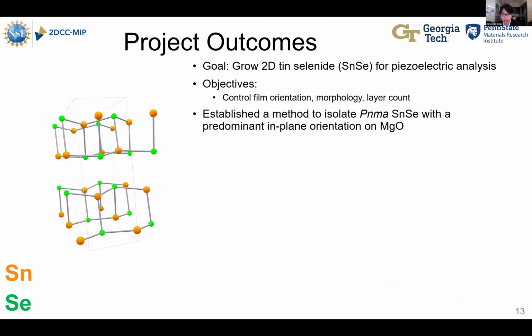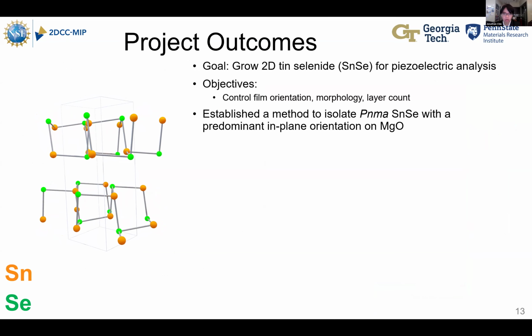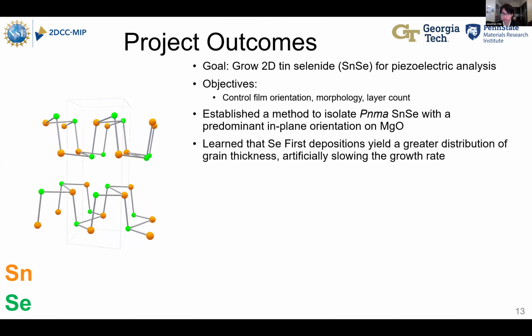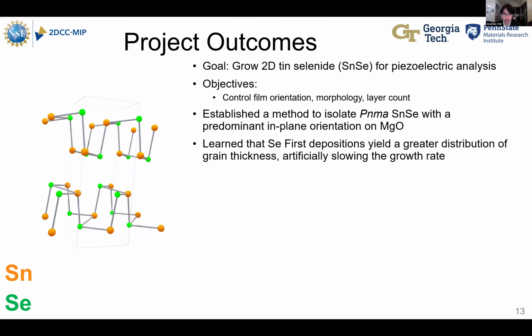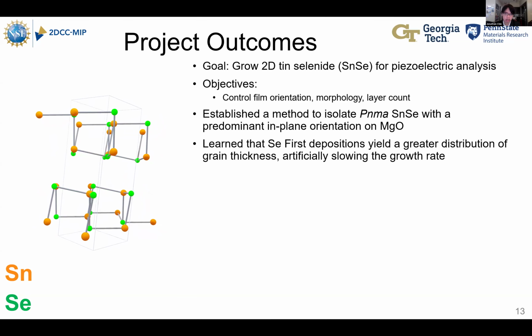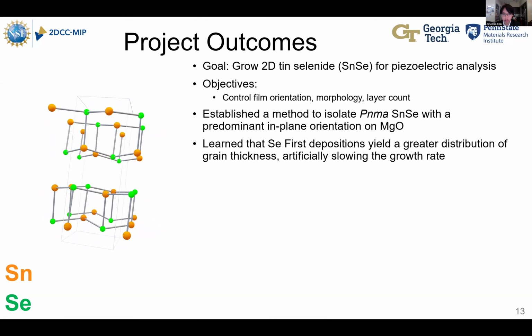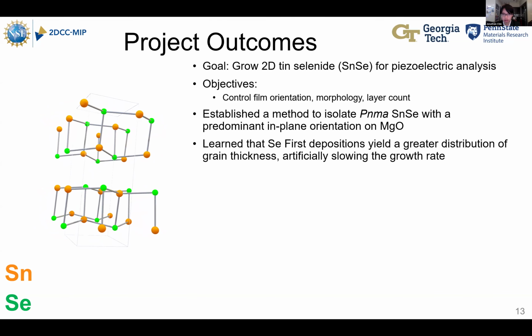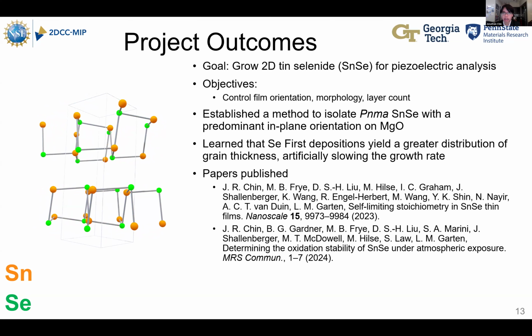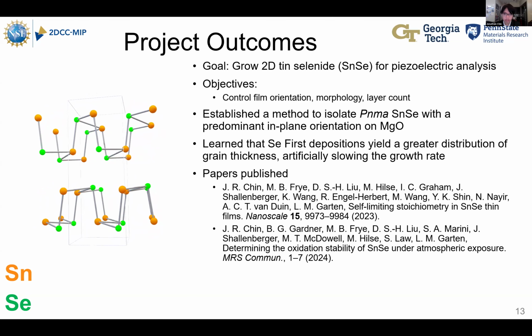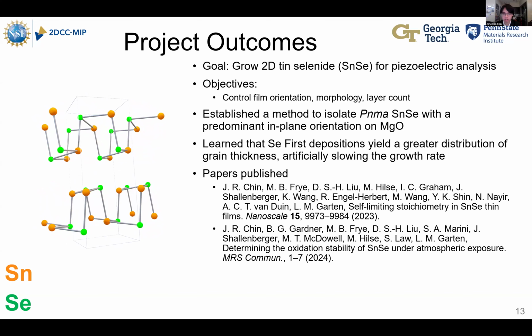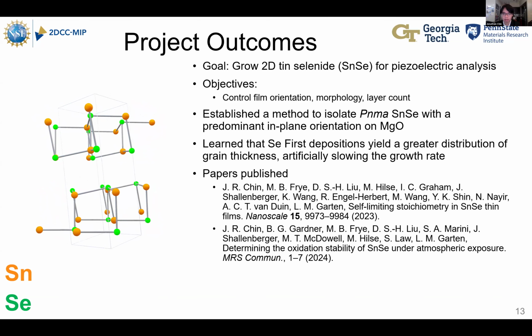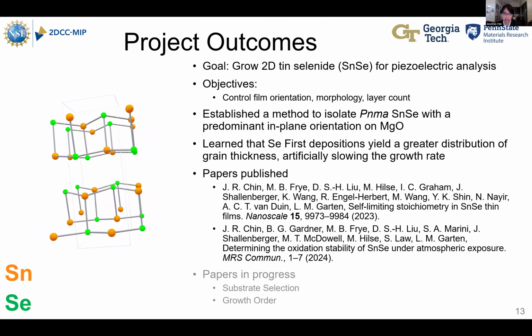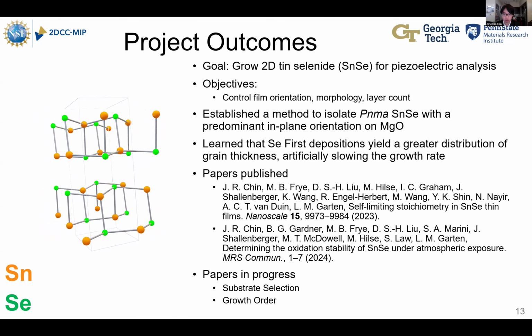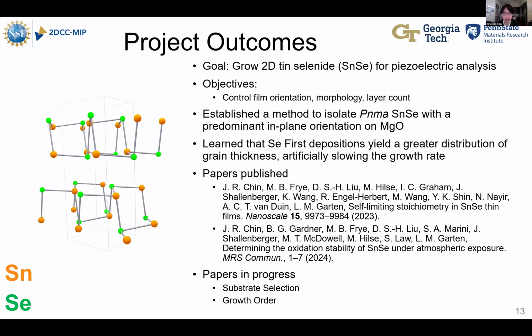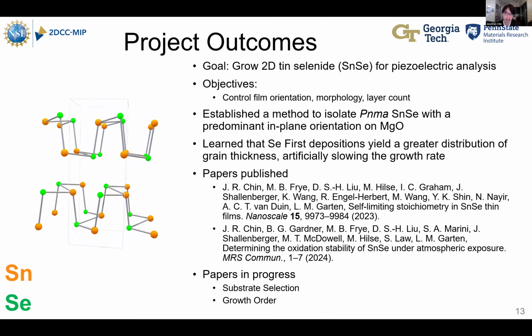So we've established a method to isolate Pnma tin selenide with that predominant in-plane orientation on magnesium oxide. Other than that, we can adjust our selenium concentration through flux ratio and growth order to help increase our overall grain areas and decrease our grain thickness. And we've published some of these initial results in a couple of papers now in Nanoscale and MRS Communications. And we have two more in progress on the work that's been presented here on substrate selection and growth order.